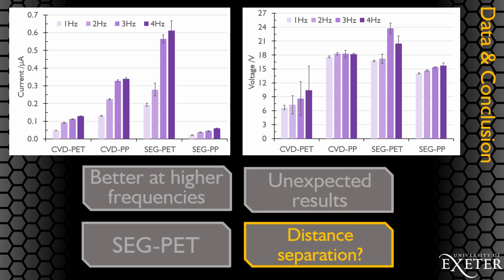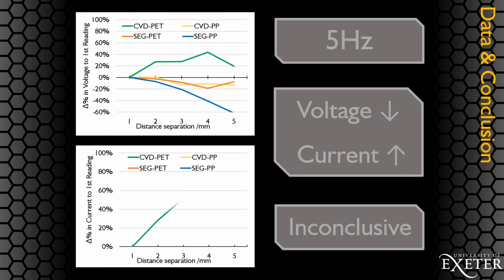What conclusions can we draw from the distance separation? These series of line graphs indicate the percentage change in voltage and current readings at increasing distance separations when compared to its first reading. Knowing prior that the better readings occurred at higher frequencies, all readings taken here were at 5 Hz. The graph seems to suggest that current increases with distance separation, particularly for CVD samples, but is seen to decrease with voltage. We are unable to draw any conclusions from this as triplicate readings were not carried out at this time owing to time constraints.